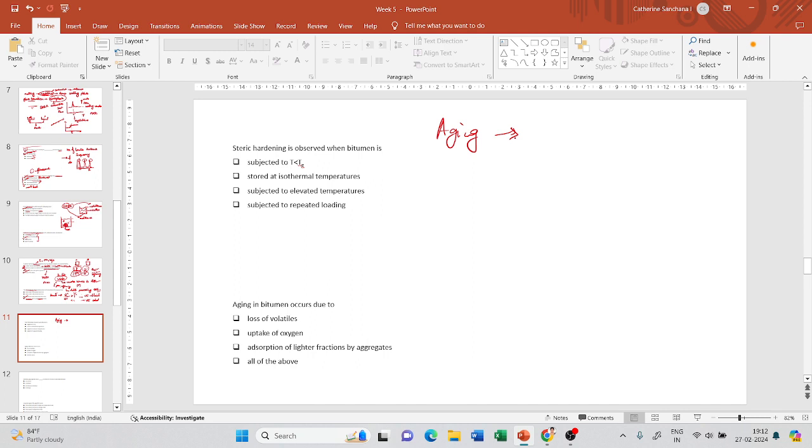The one thing which you could cleanly observe is its increase in stiffness. By doing some rheological test or consistency measure, you can easily identify that on aging there is an increase in stiffness. This increase in stiffness, when it happens due to chemical aging to be more precise, is irreversible.